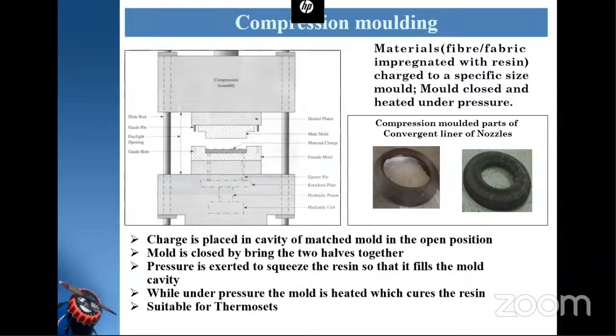Compression molding is a process where we use a hydraulic press to make the components by using a punch and die. The charge is placed in between the punch and die, and simultaneously the mold is heated and the pressure is applied to consolidate the polymer matrix composites. So here, materials like fiber fabric impregnated with resin are charged to a specific size mold, closed and heated under pressure.